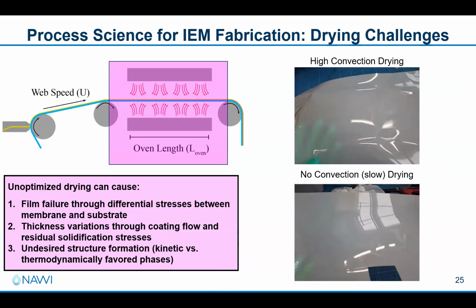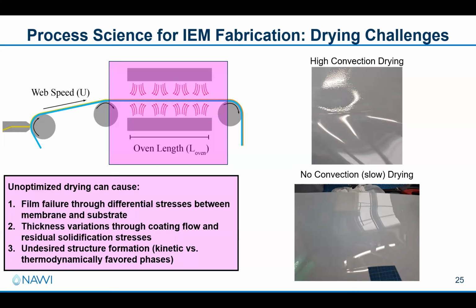And for us, on the drying side, one of the most common defects that we encounter when trying to make ion exchange membranes, just an example for some roll-to-roll cast membranes here, tends to be that orange peel texture. Because these materials are not only polymer solutions, where as they dry you can get stress development, they're also fairly hygroscopic. This kind of phenomenon can be sensitive to building humidity too. And the top image is a larger scale image of one of our membranes that's about 15 centimeters wide. And this is blown up what that texture looks like, just to give you a sense visually of what you would expect to see.